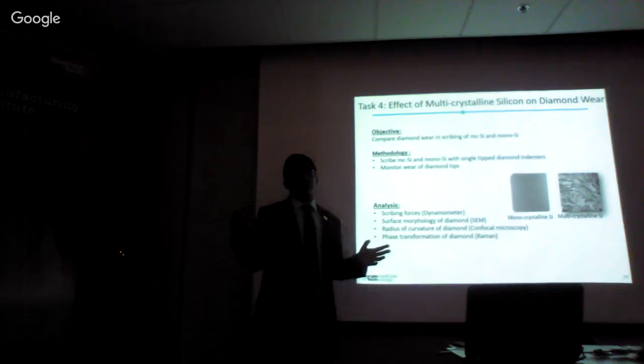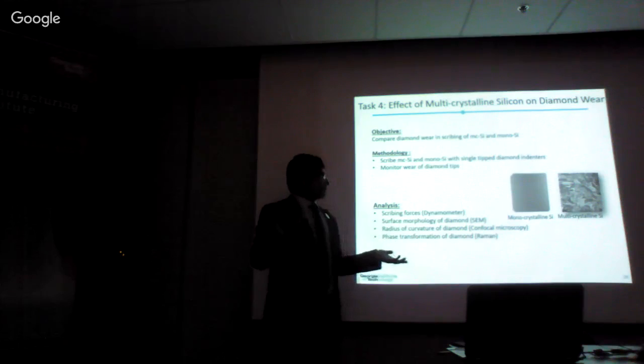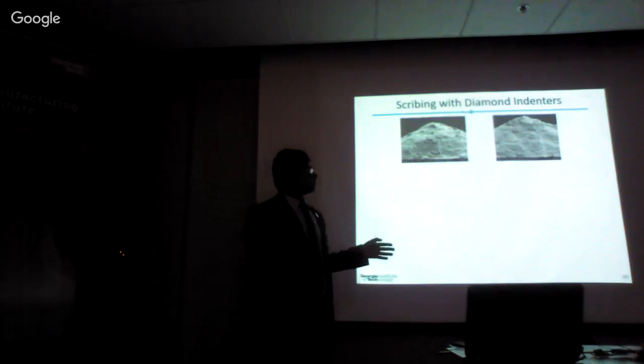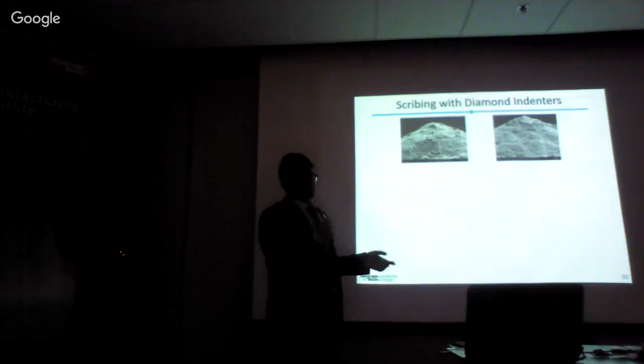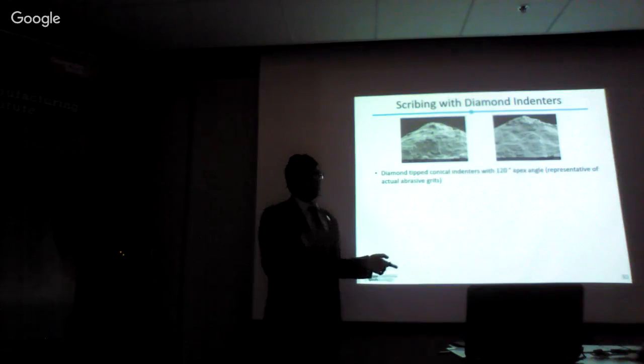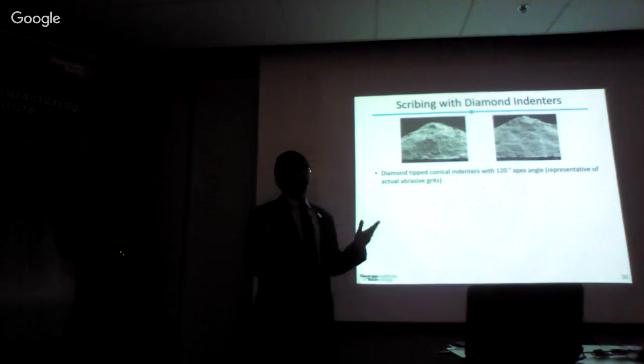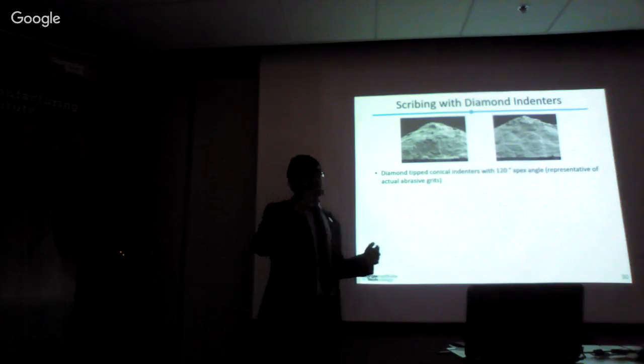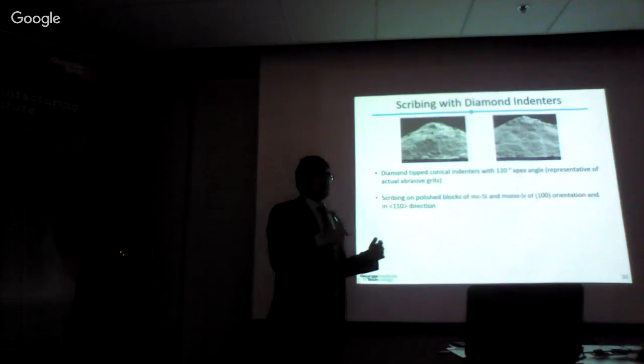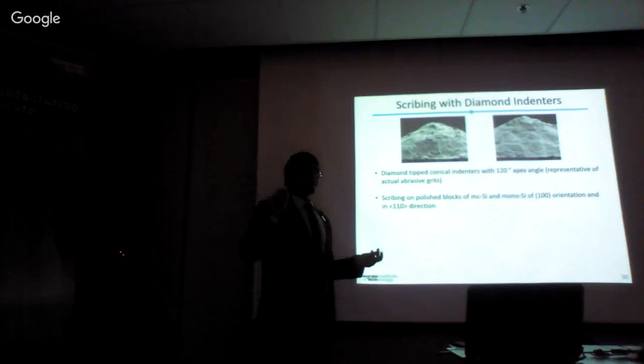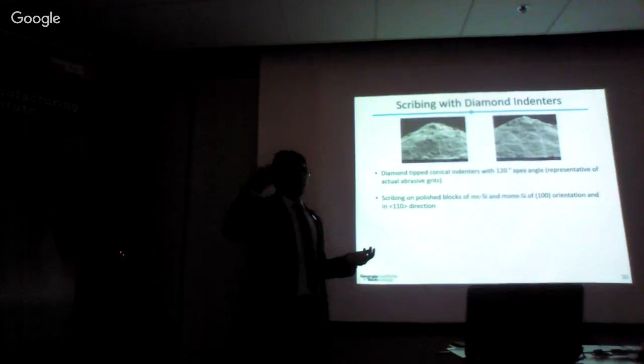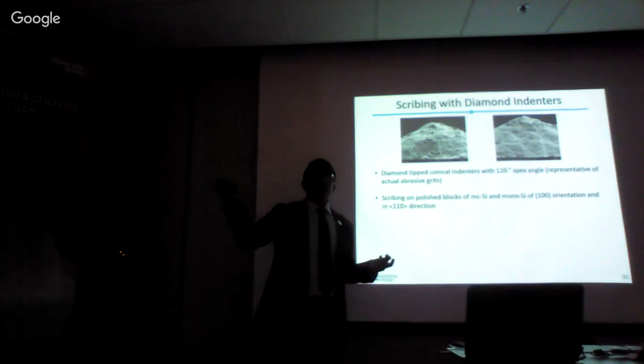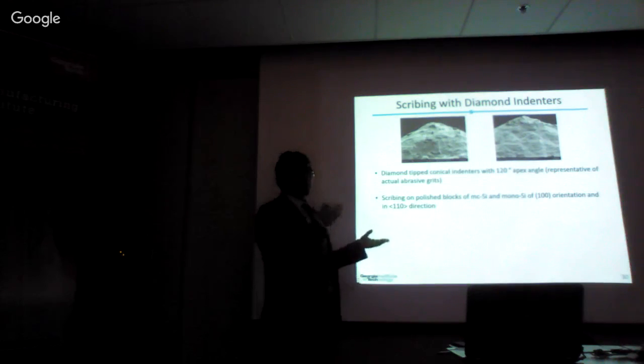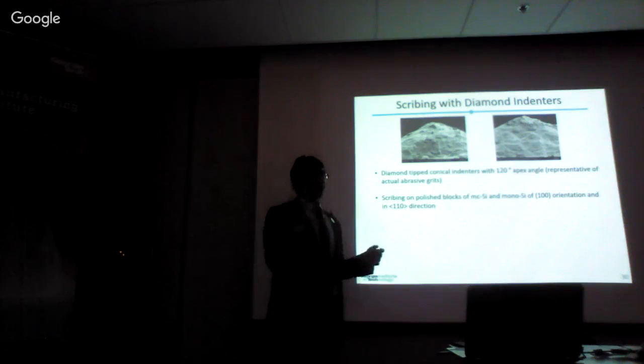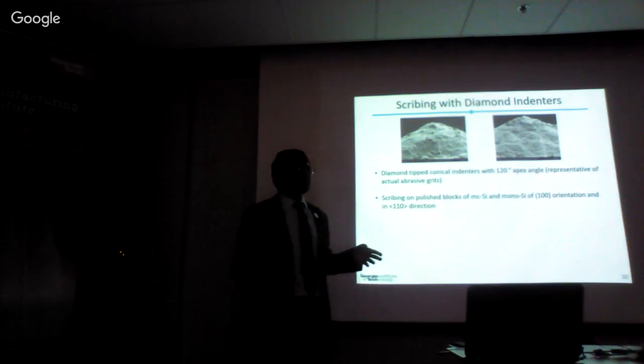to find if there is any stress-induced phase transformation of diamond. Diamond also undergoes stress-induced phase transformation at very high stresses, and that's what we want to find out. So these are the two diamond-tipped indenters. These are SEM images, with a 120-degree apex angle. This is representative of the actual abrasive shapes which we found in the first task, and that's why this shape of indenter was chosen. Now, these conical indenters are put in the scribing setup, and we are scribing on mono and multi-crystalline silicon. For monocrystalline silicon, we are using 100 orientation and scribing in the 110 direction, because in the actual wire sawing process for monocrystalline silicon, these are the main orientations of wafers cut, 100 orientation, and the cutting happens in the 110 direction.